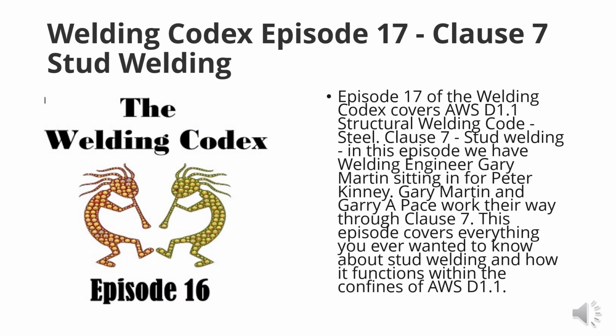So now we're up to 7.6. Stud application qualification requirements. 7.6.1. Purpose. Studs which are shop and field applied in the flat, downhand position to a planar and horizontal surface shall be considered pre-qualified by virtue of the manufacturer's stud-based qualification tests, and no further application testing shall be required. The limit of the flat position is defined as 0 to 15 degree slope on the surface to which the stud is applied. Examples of the stud application that require tests of this section are the following.